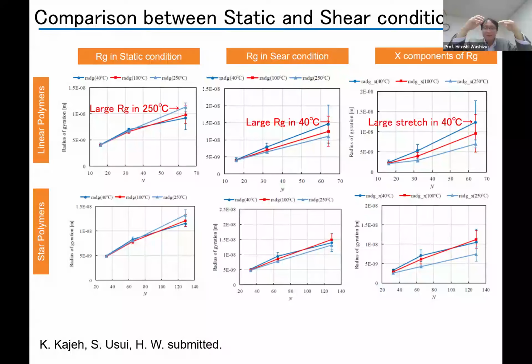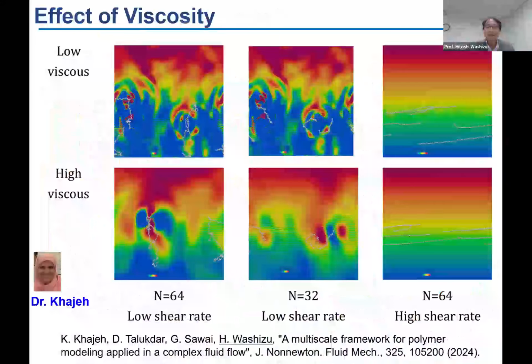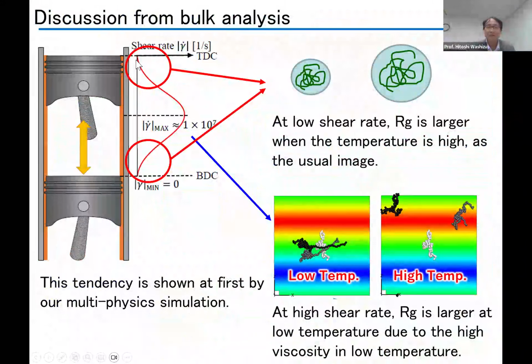So in the low temperature, the viscosity of the oil is high, so the polymers are stretched in this direction. In making some figures, it's like this: in the low shear rate, the polymers bloom up, then the viscosity rises, and so we can keep the oil film.